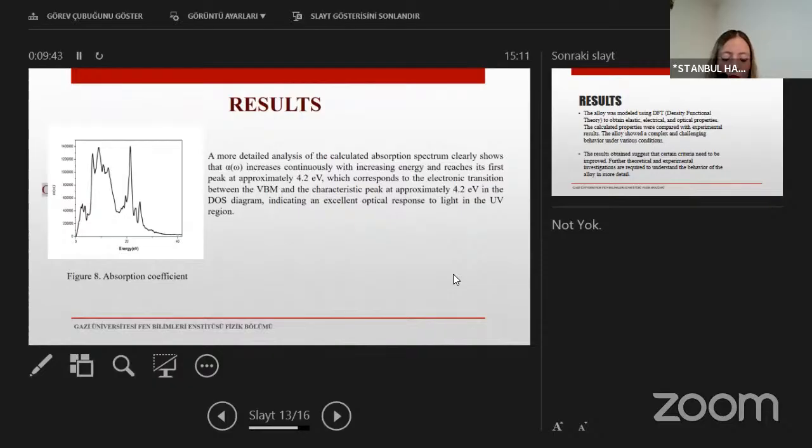The absorption coefficient provides information about the material's ability to convert solar energy and indicates how deep light of a specific frequency can penetrate into the material before being absorbed. Alpha can be used to assess the material's sensitivity to sunlight, showing how photons are captured in the relevant light range, those affecting the generation of electron hole pairs.